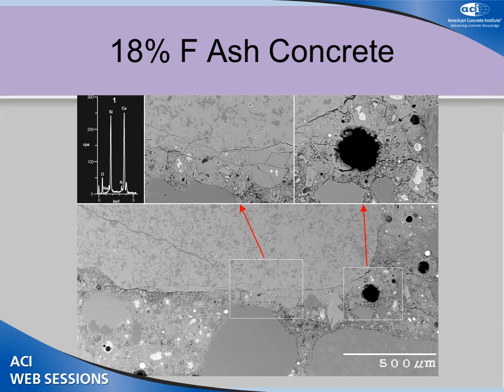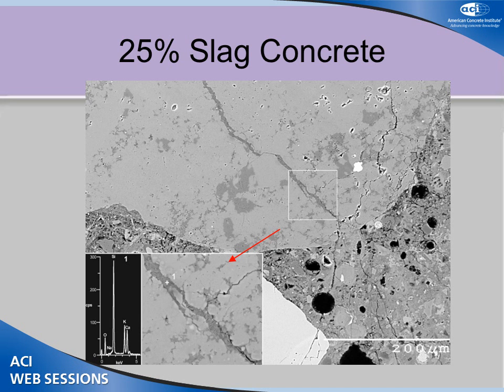This is a picture from the 18% fly ash. Again, there's some minor cracking in the aggregate. Again, there are some blow-up areas shown here. In that void, we're seeing some gel in the spots there. Again, in the void here, it's high calcium, relatively low alkali at that point. The 25% slag, again, we're seeing another fracture here in that aggregate with some gel deposits. You can see the potassium and calcium about the same height.